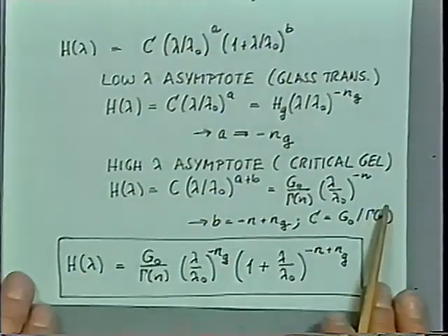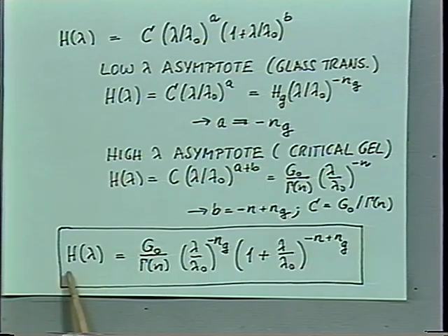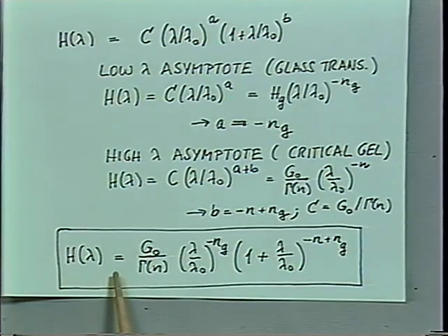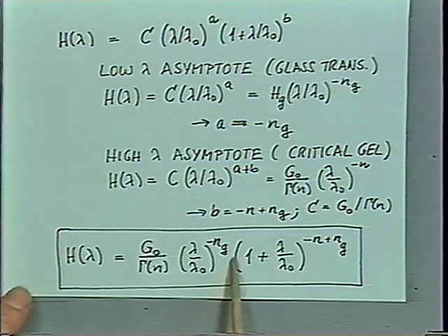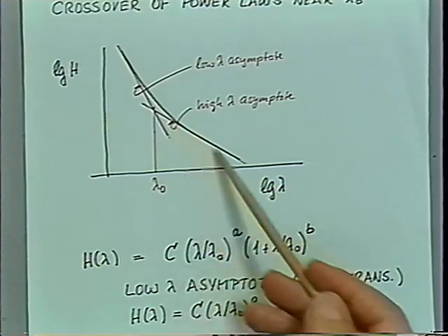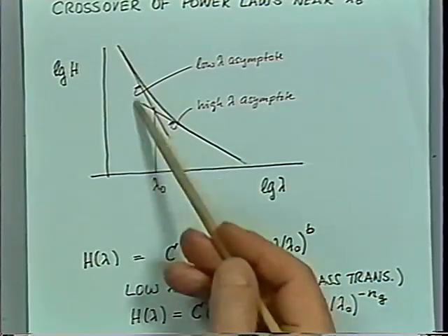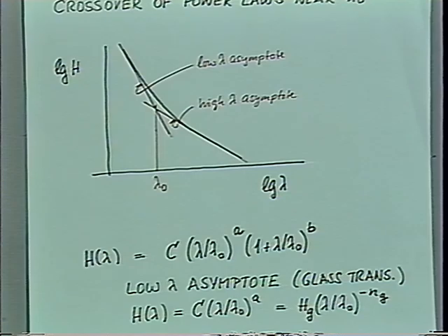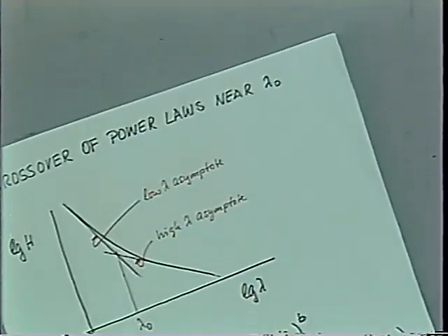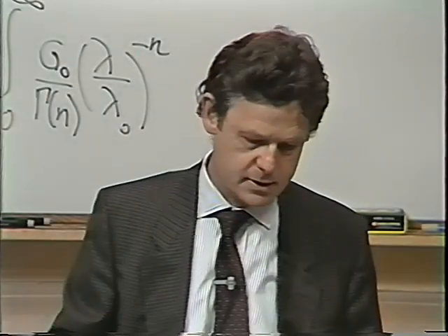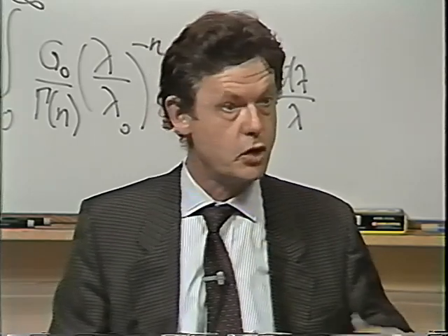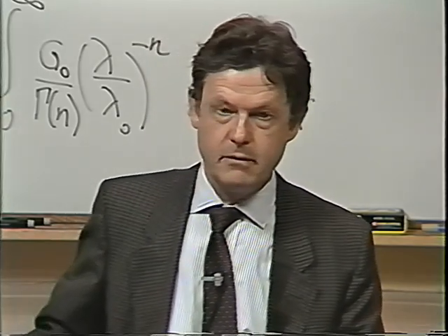So everything is determined, and we could write down the spectrum for the glass transition plus gelation given by this type of power law. That's a linear superposition. It's just a heuristic approach where we know that the asymptotes are accommodated. The quantitative agreement in this range has to be studied and has to be shown that this is okay, and we haven't done that so far. But that would be a simple way of accommodating the transition, which we shouldn't neglect.